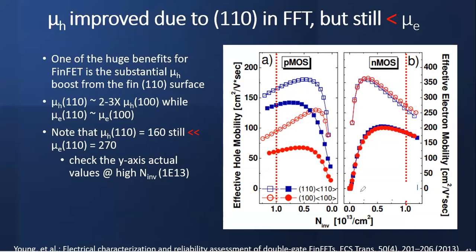Let's look at these pictures. This is the inversion density of 10 to the 13 here. If you look at the comparison, of course, 100 is a round circle, and here in pMOS, this is 100, so your hole is not good, and here your N is pretty good. And if you do 110, which is a square, you move up pretty good, like 2x. You move on at 2 to 3x, close to 2x. But look at the axis.